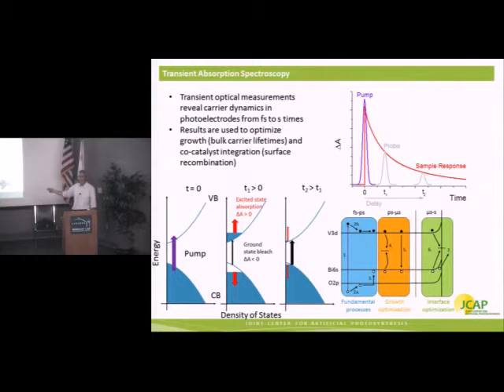So we can do transient absorption to measure carrier dynamics in the material over a wide time range. So from femtosecond timescales, where you have fundamental hot carrier relaxation processes, to picoseconds and microseconds, where you have these excited carriers recombining, both electrons and holes directly combining across the band gap, as well as these carriers being trapped at defect sites. And then interestingly, we can also look to very long time scales, where the only carriers that still remain in the material are those that are charge-separated states.